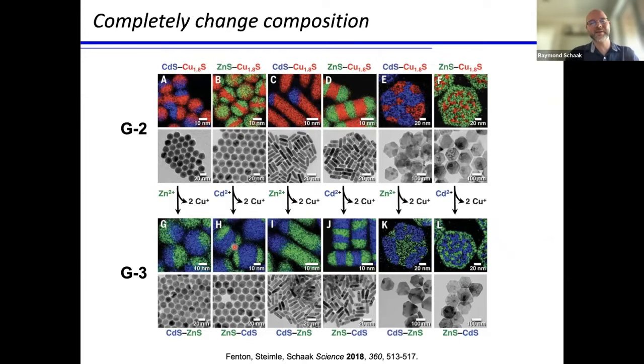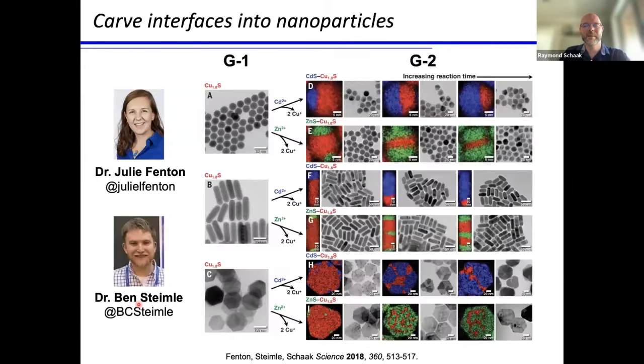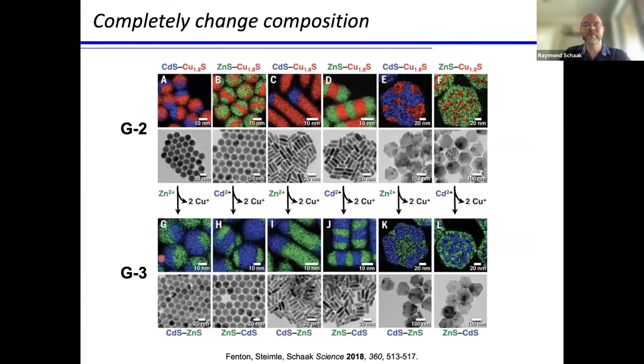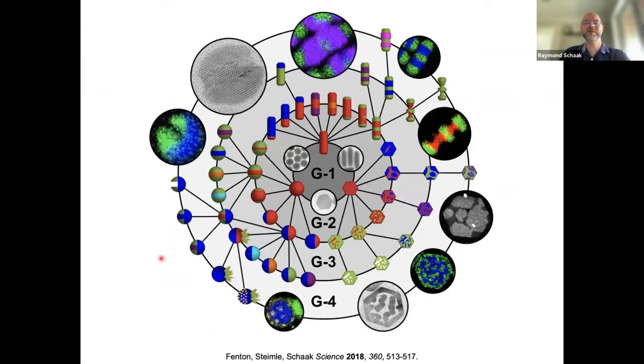And basically what that does is it produces derivative nanoparticles through this transformation pathway that maintain the shape and size and uniformity defined at this first generation, the interfaces defined at the second generation, but now have completely different materials incorporated within them. No copper sulfide remains. And so from a transformation pathway, what starts to emerge, this is a beautiful graphic that Ben had designed to go along with this paper. These 3 simple copper sulfide starting materials can be transformed, in this case, into 47 derivatives just through the sequential application of partial cation exchange chemistry.